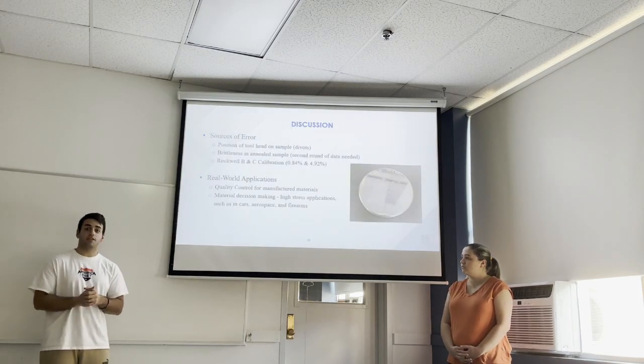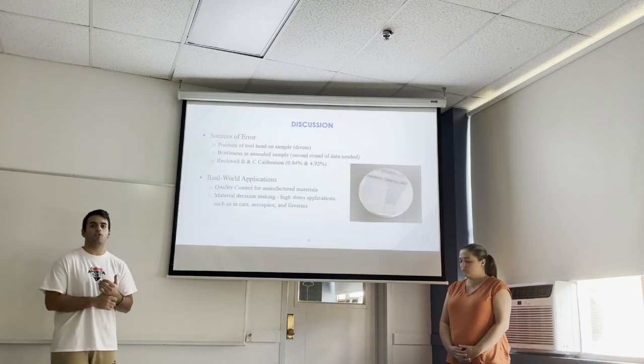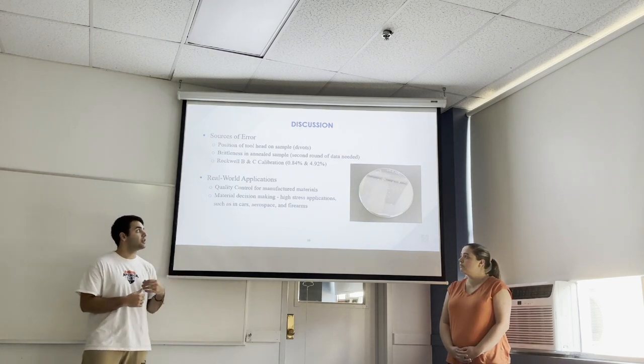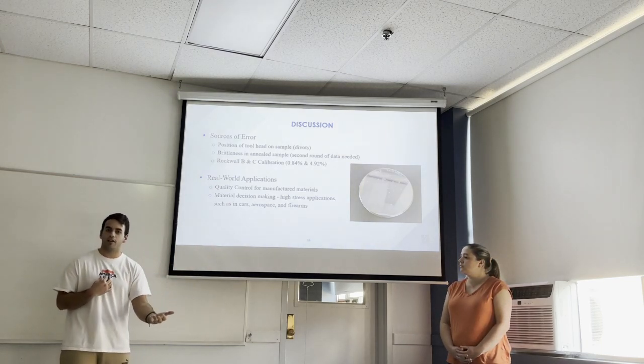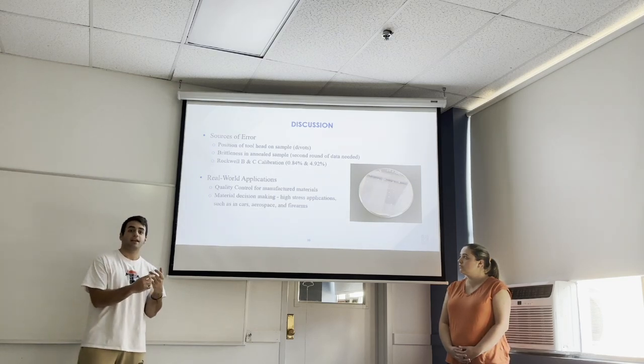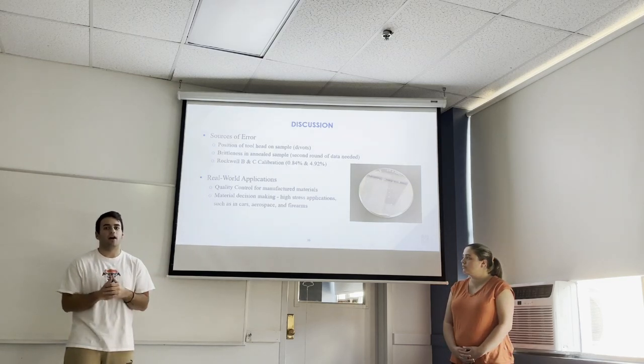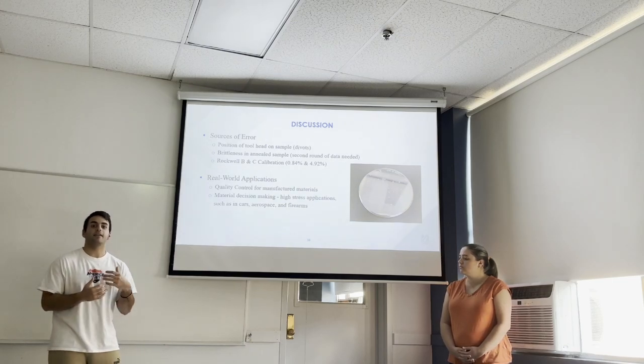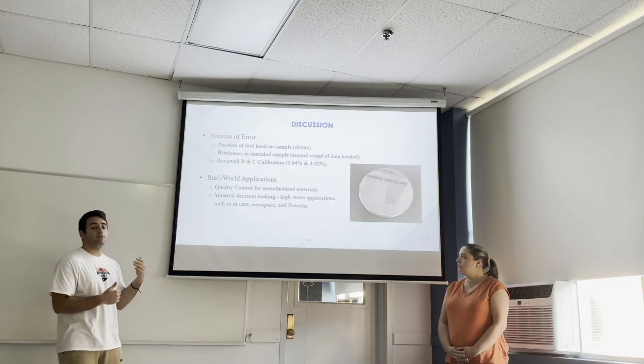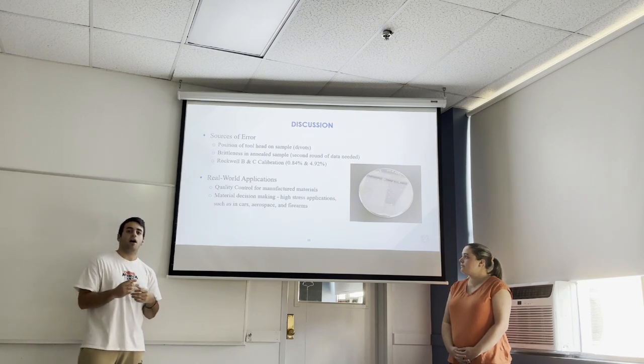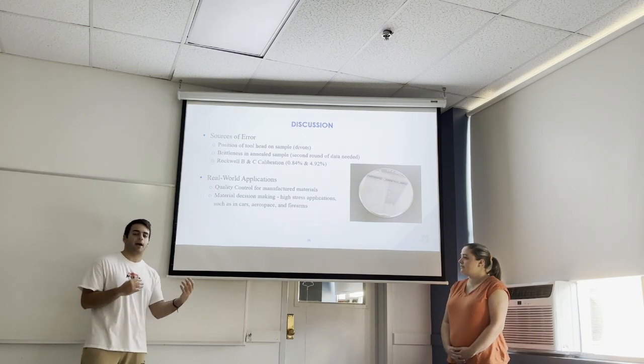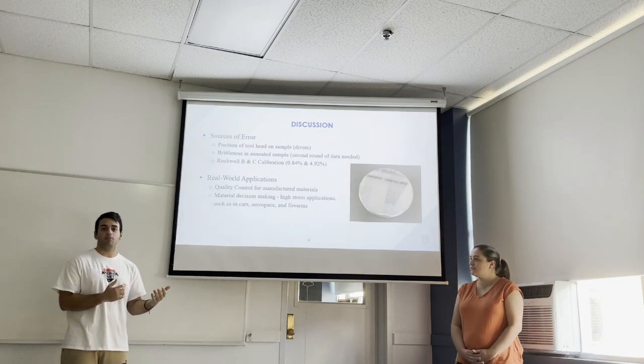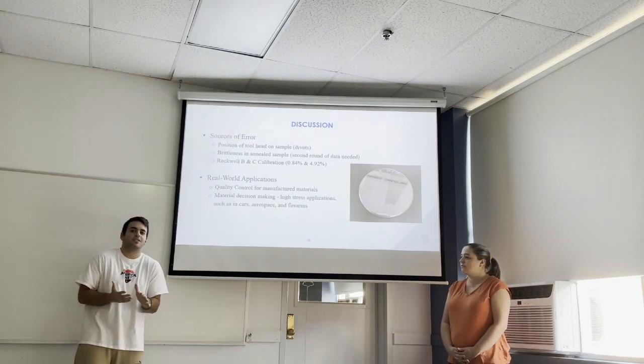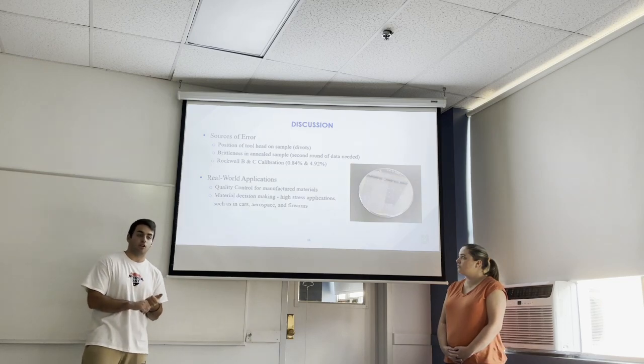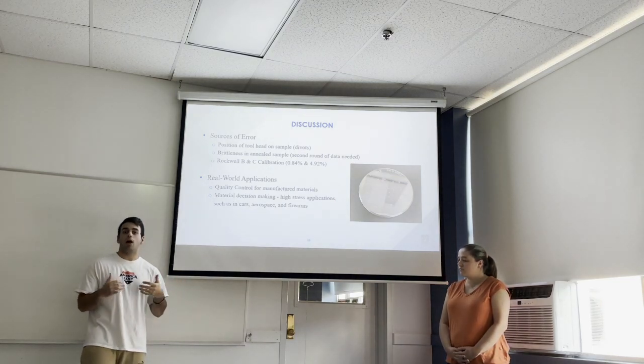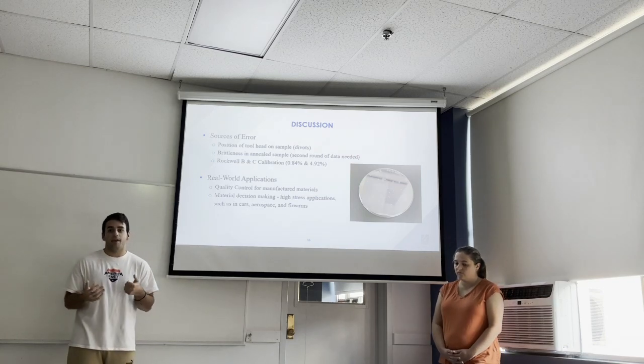All right, so some sources of error for this could be the calibration of the Rockwell B and C tests. As you can see pictured here, here's our calibration disc. It has some divots on it. So if we were to use those calibration and hit a divot point, that would unexpectedly change our found hardness values. So another thing could be a brittleness in the annealed sample of 1045 steel. We actually had to swap out our sample and use a different sample because the first annealed sample was non-conclusive to our results and trends. So the second sample, while it was more conducive to our results, it still could have had some brittleness affecting the results.